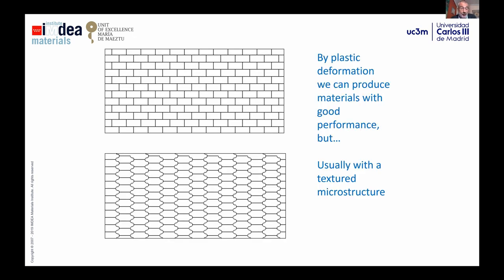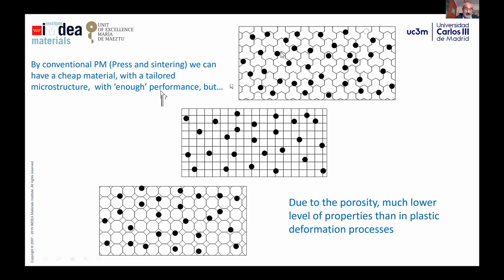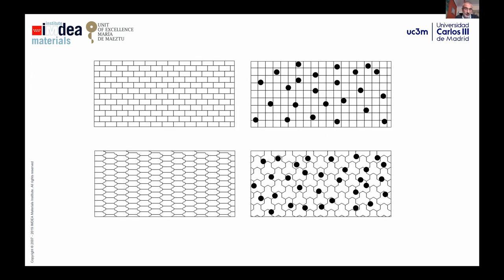So in general, if we want to compare powder metallurgy with the conventional plastic deformation methods, in plastic deformation methods we have a simulation of a microstructure. Here you have a textured material, usually without any porosity, with a low level of defects, but with a textured microstructure. If we go to powder metallurgy, we have these black dots simulating the porosity, but by conventional powder metallurgy, by press and sintering, we have enough performance to fulfill the application that we are looking for, but we have a lot of porosity. That means a lower level of properties than in the conventional plastic deformation processes. So we can compare on the left the typical microstructure in a plastic deformation process, and on the right the conventional powder metallurgy microstructure obtained by press and sintering.